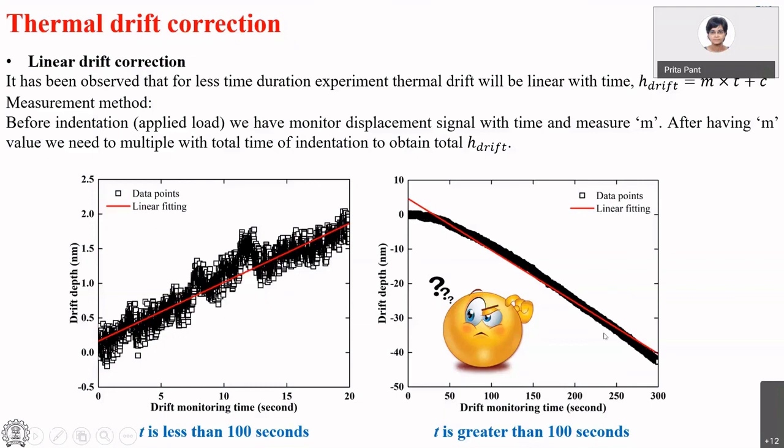The red line again is a linear fit. And if you take this fit and you do this correction in your data, you're probably not going to be correct. So point number one, be aware of the corrections to the data that are already done by the software that you're using. Point number two, don't completely trust that correction. Evaluate for yourself whether it is working for your experiment or it isn't working for your experiment.